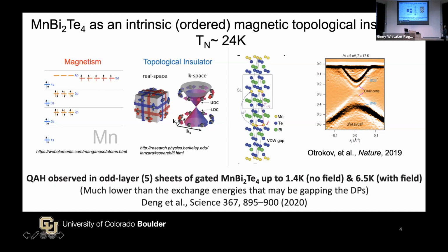Okay, so this material has septuple layers, 7 individual layers with the manganese at the center. That's in contrast to standard bismuth telluride, which is quintuple layers. There's 5 layers in a typical bismuth selenide or bismuth telluride. So here we have 2 extra layers, septuple with the magnetic manganese element in between.